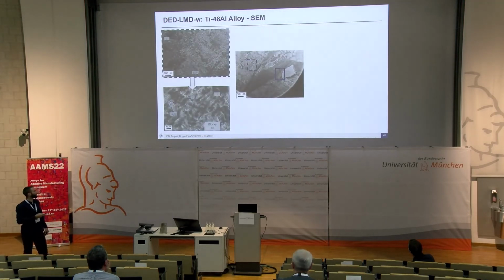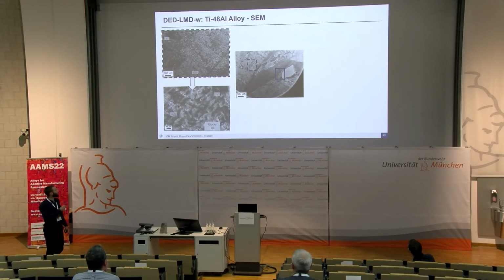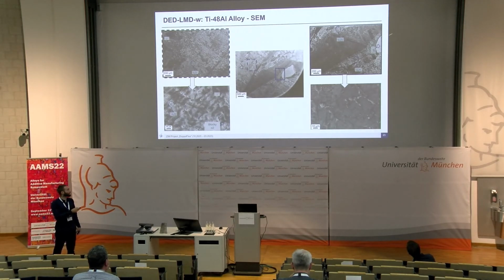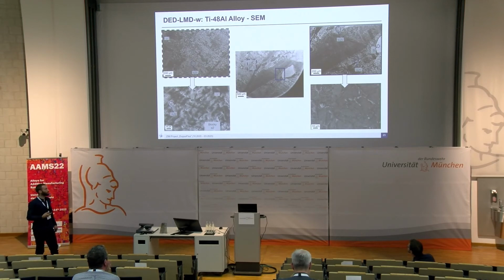So let's have a closer look at the microstructure. We see these gamma phases, we also have these alpha 2 gamma phases, and we also have some blocky alpha 2. That's all normal, and with heat treatment we can homogenize this microstructure. But what is not normal is this here. This is a complete titanium inclusion, which means our titanium wire wasn't melted completely. So that is one thing we need to get more control of.